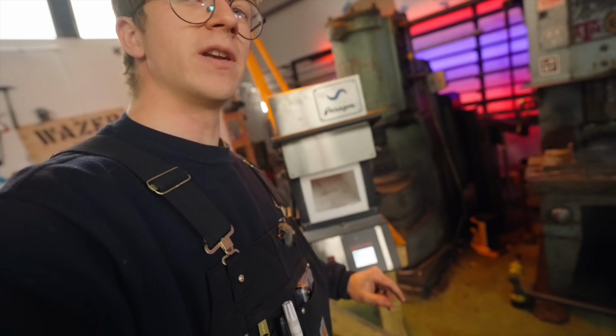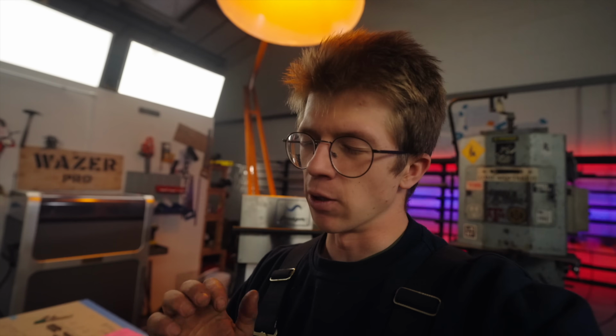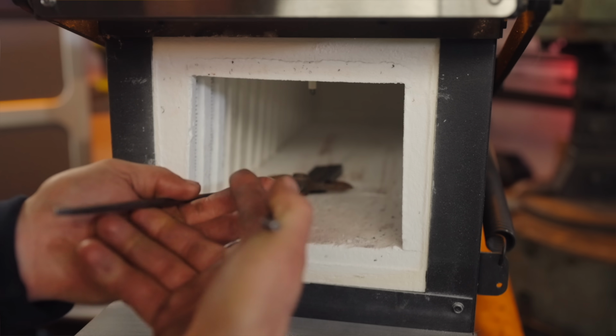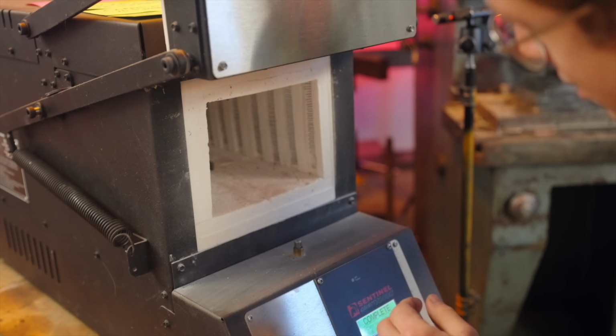I'm gonna air out the oven, get it down to 250 degrees Celsius, 400 and something Fahrenheit, and we'll do some tempering cycles on the pieces. I know a lot of you guys know, but when you harden steel by quenching it, in this case in oil, it becomes incredibly brittle. But in order for it to be serviceable as a knife or a tool, we bring it up to a lower temperature, hold it there for a little while. That's called tempering, and the steel then regains a lot of toughness. 2 tempering cycles are done.